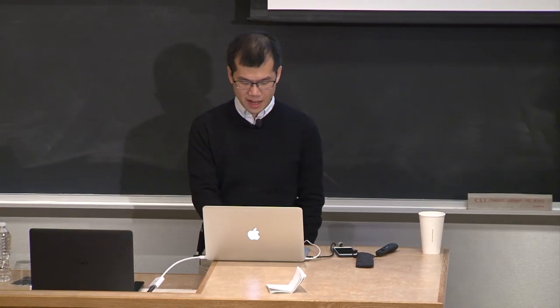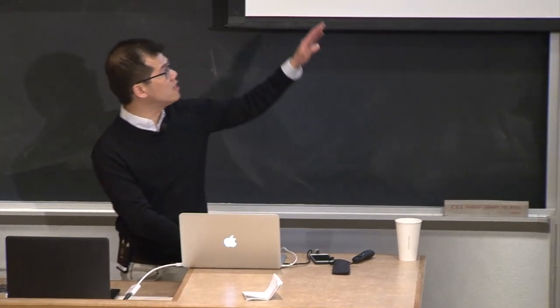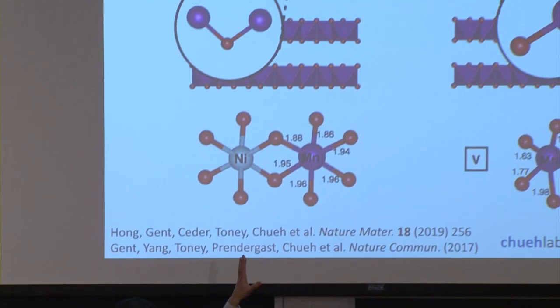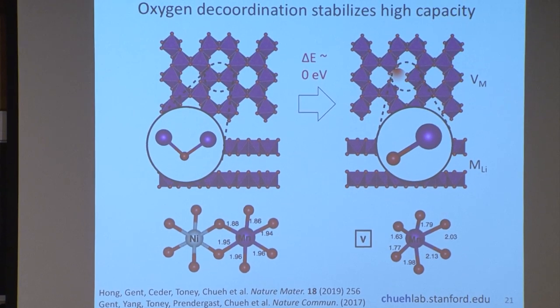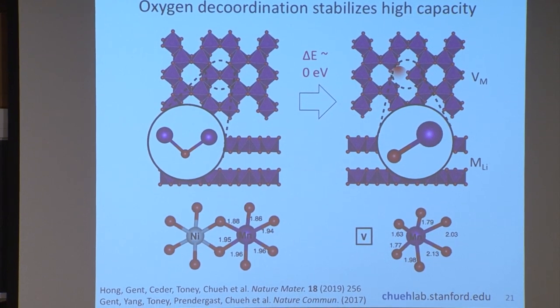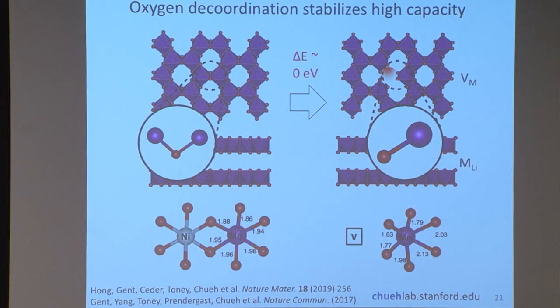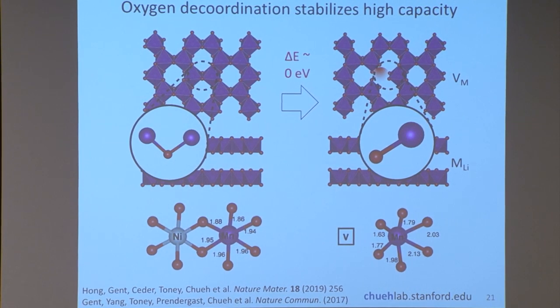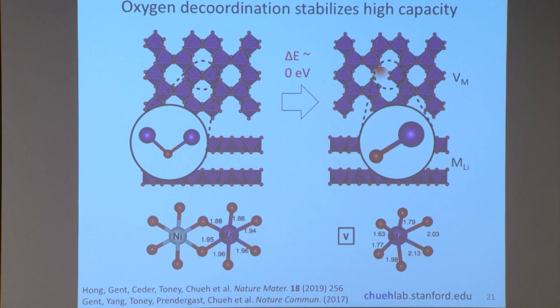So if you look at some of the ideas I mentioned here, in terms of these metal vacancies, they can actually be generated thermally as well. So if I can generate them ahead of time, then I can begin to modify the property. So you can deviate from equilibrium. And the other aspect is that by understanding the defects, you can also think about changing the composition of the material.